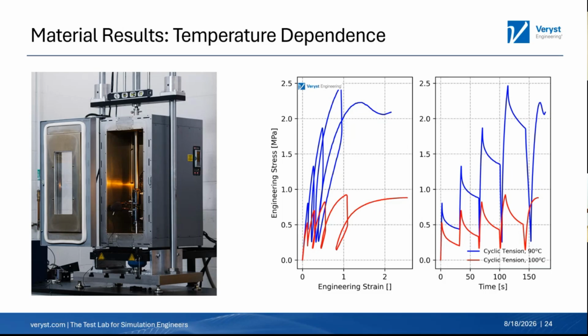So that loading and unloading we find is very important to help understand the time-dependent behavior of the material, because we measure that stress relaxation at multiple strain or multiple stress levels to understand how linear or non-linear it is. One thing to call out here is that there's a large difference in the material response between 90 C and 100 C, right? So at 90 C, we peak at about 2.5 MPa, whereas at 100 C, we're at just, we'll say, 0.9 MPa. So that's a 2.5x difference. So there's a large stiffness difference.